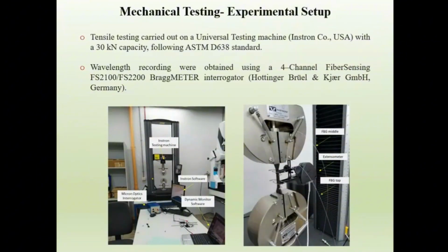So this is the experimental setup. You can see here we have the specimen with the three FBGs, on the first layer, in the mid plane, and on the 16th layer, and also we attached externally an extensometer. So in a sense, we are measuring the strain due to mechanical loading simultaneously from an extensometer, as we usually do, and also in situ by using the three sensors embedded in different layers across the specimen.